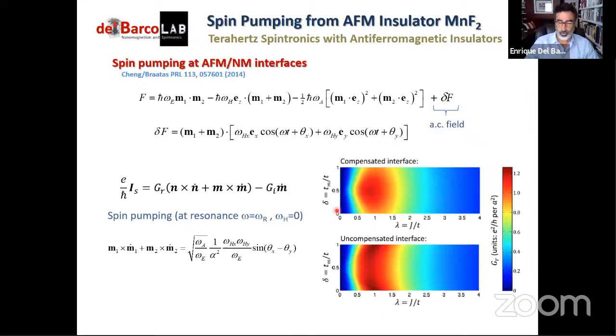And this is something that you can be seeing here. A compensated interface basically means that the last layer of the antiferromagnet adjacent to the non-magnetic layer is an antiferromagnetic layer. And an uncompensated interface is just basically when the last layer is a ferromagnetic arrangement. And they don't see very substantial difference, and they predict the spin mixing conductance on the order of one quantum conductance unit, as you can see here. And actually, as I will show you, the results tell us the same thing.